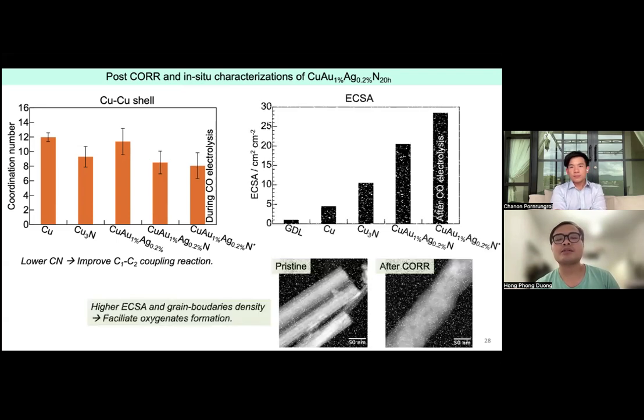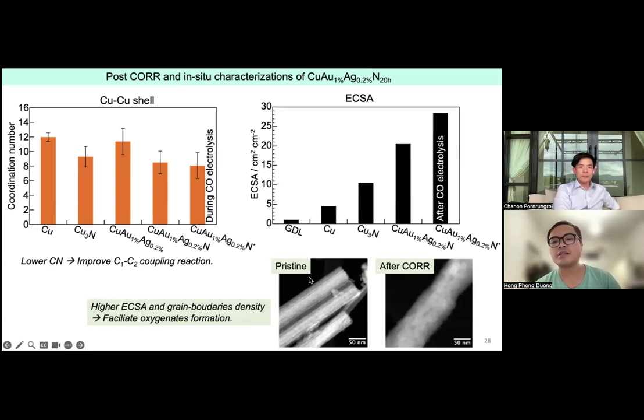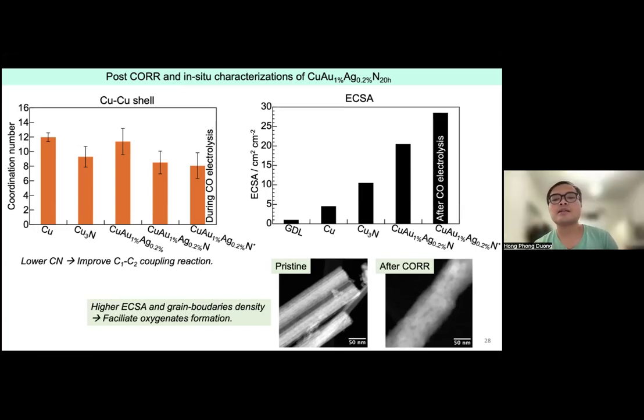Another thing is we performed measurement of the electrochemical active surface area, and we found the sample after electrolysis shows a much higher ECSA, as shown here, which was confirmed by the TEM observation. We found the grain boundary density of the sample after electrolysis was much higher, and in some previous literature, this can boost the formation of oxygenate products, which is important to make alcohol. And this result, in fact, at the time of publication, was also the highest value of Faradaic efficiency for ethanol and propanol altogether from CO reduction, with almost 76% efficiency.